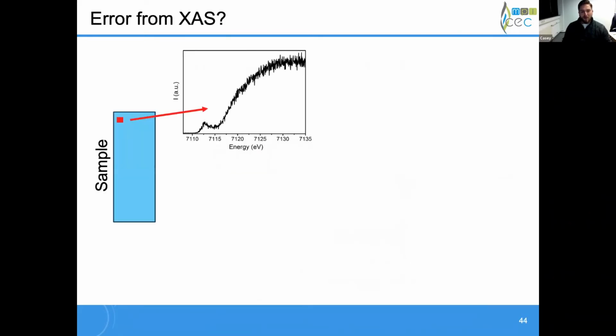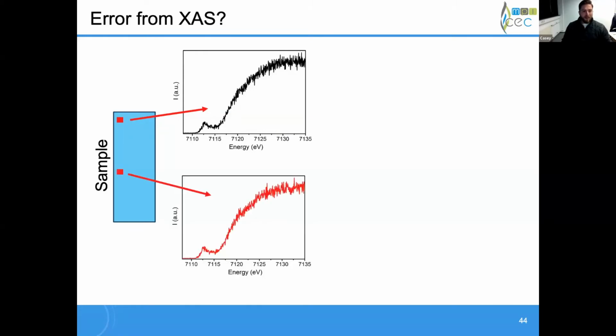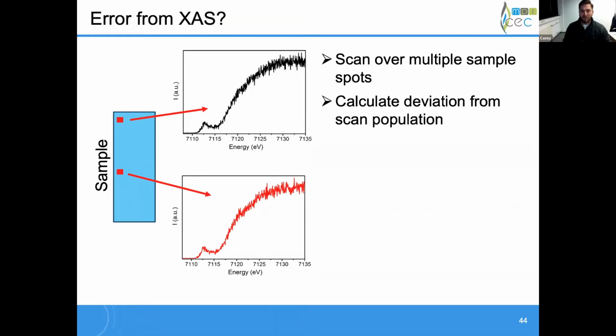So if we remember how we actually do this experiment, as most of you know, we usually pick a point on a sample, we irradiate it, we do damage studies, see how long you can irradiate it before shifting or changing the chemical nature of your system. And then we set something below that as our total scan time, and we collect a spectrum. Then we move to another spot and we collect a spectrum, and we keep on going over the sample, collecting spectra until we're happy with our signal to noise ratio, or that it looks clean enough effectively.